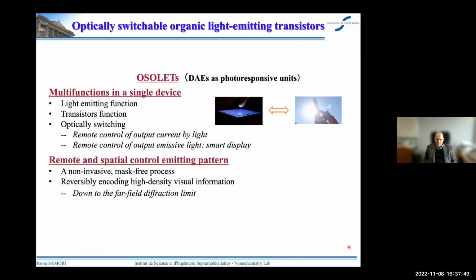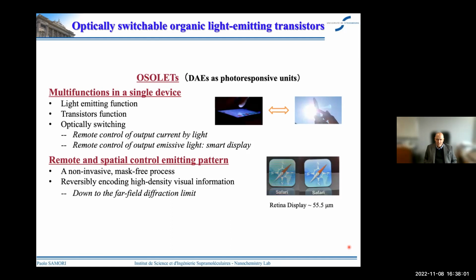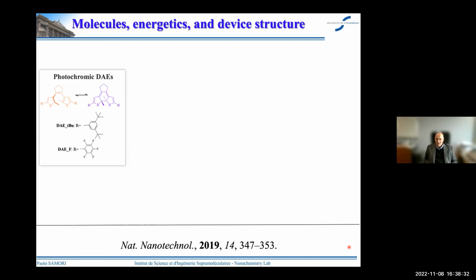We can reversibly encode high density visual information, and we can do this at a level that is below the far field diffraction limit. Now, bear in mind that the best displays that you have accessible are those based on retina, which has a resolution of about 55 square micrometers. Our approach will actually bring us down to 1x1 square micrometer. And so we can have a control, you will see, over the visible spectra in terms of operation in the green, blue, and red. Now, how we have done that experiment is pretty simple.